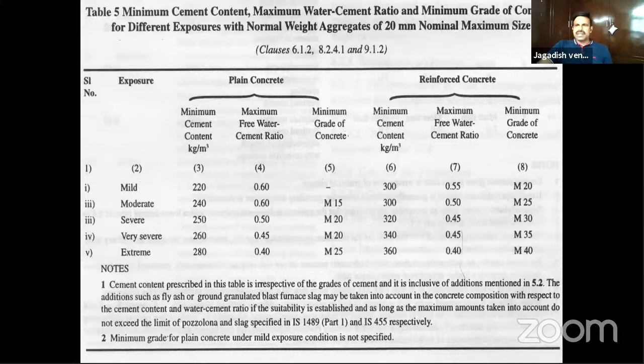So if you have to design the concrete mix, you have to design based on the exposure conditions. Suppose you are in a mild environment, designing two elements like columns and foundations. For the column concrete, in a mild environment, you are designing for M20 grade of concrete. However, the foundation, which is buried under the soil, comes into the moderate condition. So the minimum grade of concrete you have to design is M25 grade because it comes under moderate condition. So in the same environment, the element also matters, because the concrete element buried under soil comes under a different exposure condition, and you have to go for a different minimum grade of concrete.